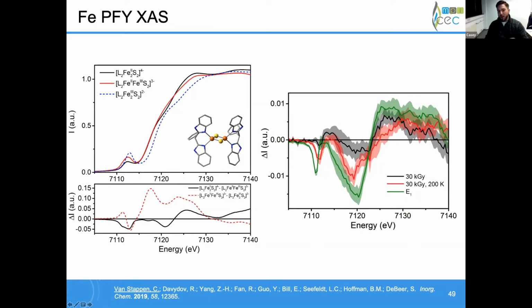What's more is that when we compare our cryo-reduced sample in black with the cryo-reduced annealed sample, the cryo-reduced annealed sample seems to be gravitating towards our E1 state. And I can also mention here that some of the differences we're seeing is because when we do the cryo-reduction, we also generate a very small amount of oxidized P cluster, and that can account for basically the differences we're seeing here. But that's another story, or one for questions. So it looks like we have something that is an iron-centered reduction, and not just iron-centered reduction, but something relatively localized to an iron-3 center.